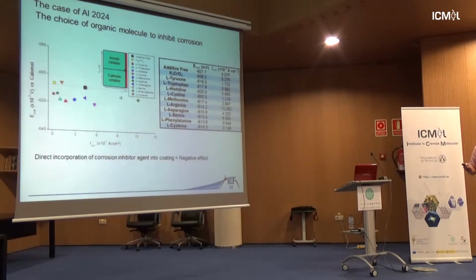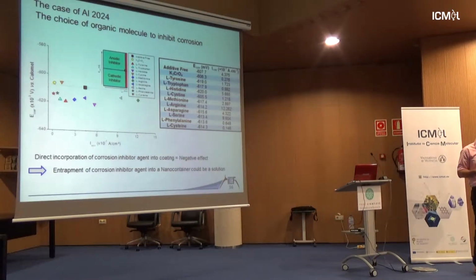So we have tried this, because we were interested, as I mentioned, in the green aspect. So if you want to replace a nasty CMR agent, it's better to go a step further, so to select a green material. So we ended up selecting amino acids, and all these amino acids have been tested alone, by themselves. Here the yellow circle is chromate, and you can see that from the position of the substrate itself without any additive, it's a little bit higher, so it's anodic protection. And what we have tested here, that's the L-cysteine, for instance, it's a cathodic protection, and that's the phenylalanine.